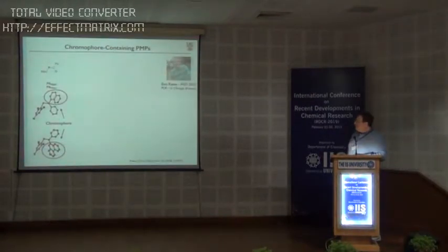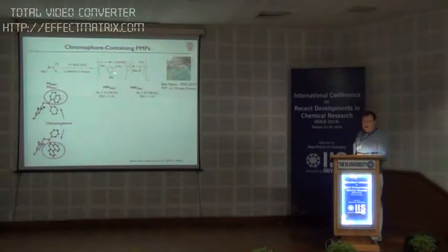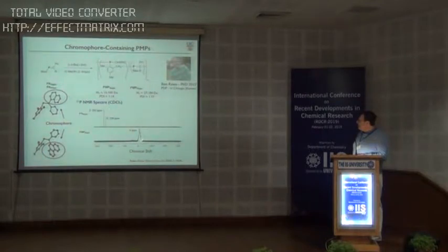So we made these phosphaalkenes with naphthyl and phenanthryl groups. So these are our chromophores now. They're UV-active chromophores. And you can polymerize them, we can make polymers, we've seen all this kind of stuff, we can characterize them, they have this crazy isomerized structure. And we can show that unequivocally. Here's some NMR: the polymer's broad, polymer signals are always broad, the monomers are sharp.